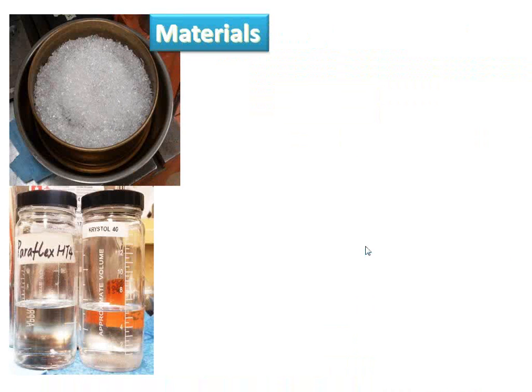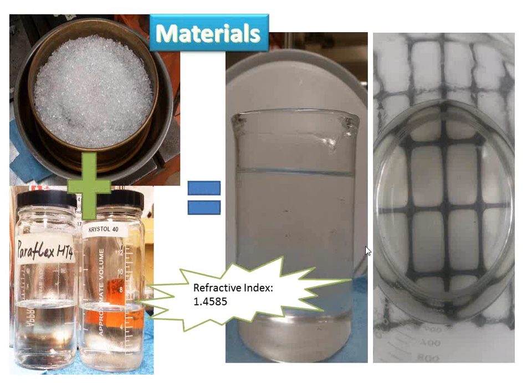Well, it's not magic. It's a little bit of physics. It turns out that if we get a special aggregate, fused quartz, high-quality fused quartz with little impurities, and we measure the refractive index, and we come up, to the third decimal point, with a mixture of oils, so that we have the very same refractive index as the fused quartz, that becomes transparent.